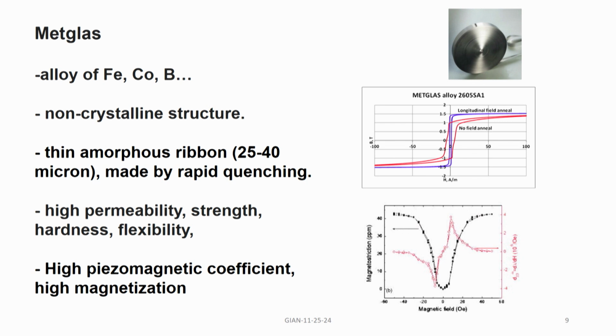That is this loop, and the first derivative of that is the piezomagnetic coefficient. That is what is shown here. It starts from 0 and it goes to a very large value, and when the magnetostriction saturates, Q goes to 0, because once it saturates, the slope is 0. So, with this rapid rise in the magnetostriction, the derivative starts from 0, peaks where the slope is maximum and drops down to 0, and it is symmetric. Okay.